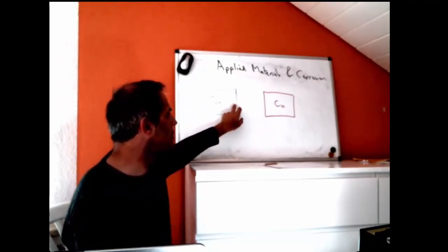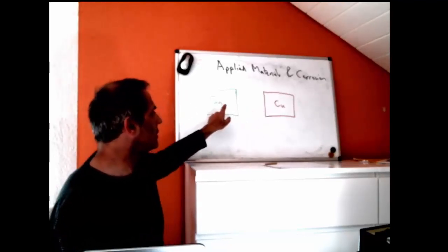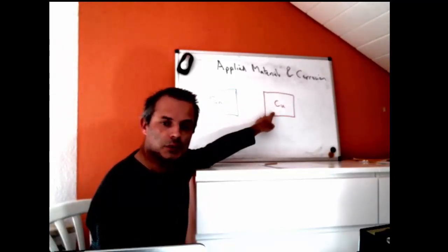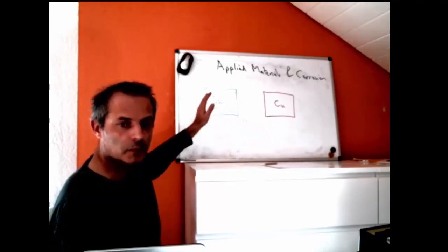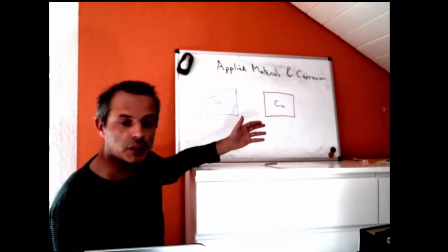energy. If we take another metal, copper or platinum in their examples, and we attach it to the tin, then we will see that hydrogen forms on the copper and the tin dissolves. That's because the whole metal block is pulled to the voltage of the tin. The hydrogen forms on the copper because it can form on there easier because the overpotential is lower, and the tin dissolves. This is an example that brings us closer to our title, because this is a type of corrosion